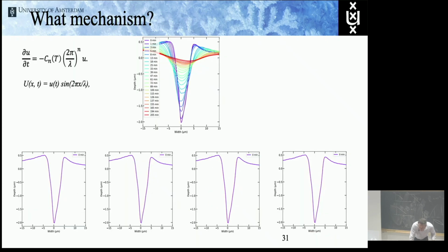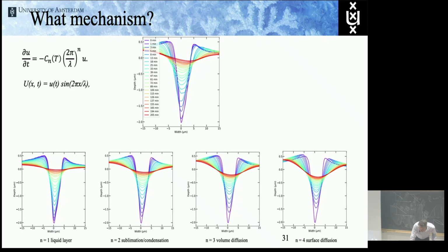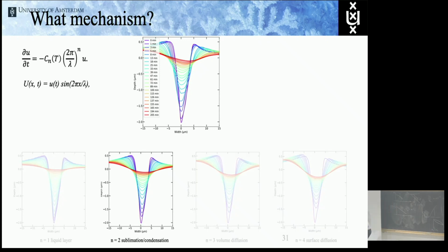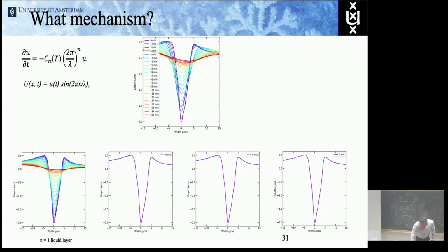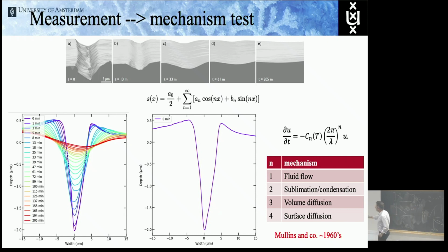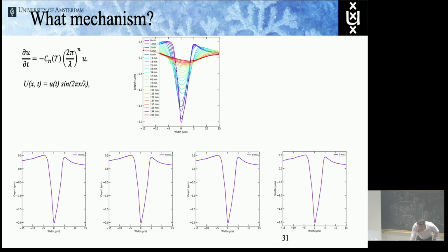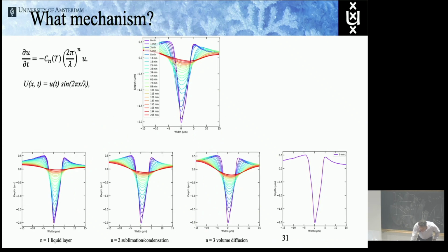And so what we do is we write down the equation. We describe the profile as a Fourier sum, and for each of the Fourier components, we can do this calculation and then see whether n equals 1, 2, 3, or 4 is the winner. So what we do is for n is 1, 2, 3, 4, we start out with the initial profile, because that's our initial condition, and then we simply evolve the solution in time with the n that we want.